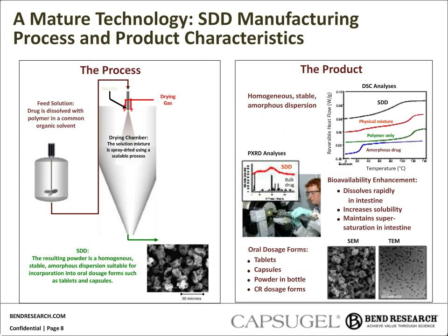This slide is a high-level snapshot of what we're talking about when we say spray-dried dispersion technology. Effectively, we take drug and a high glass transition temperature polymer and dissolve it in a volatile organic solvent. That solvent stream is then pumped through an atomizer into a drying chamber where hot drying gas flashes the solvent off of the atomized droplet, creating rapid drying kinetics and essentially freezing that solid solution into a dry powder particle state. And we'll talk more about exactly what that particle consists of in the coming slides.